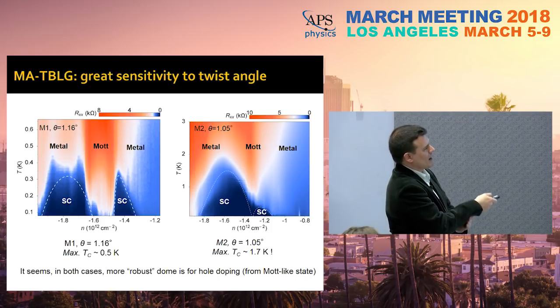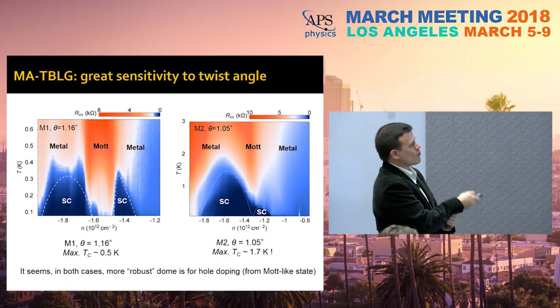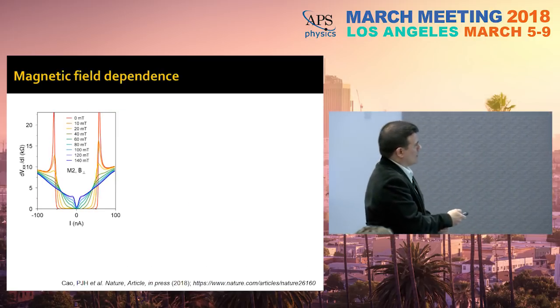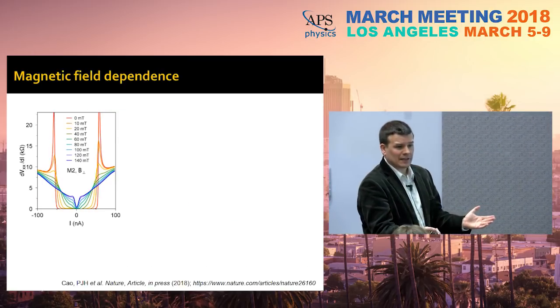There's a bigger asymmetry now. This has actually a much higher TC at optimal doping of about 1.7 Kelvin, okay? We seem to always have a more robust dome for holes than for electrons, very similar to the cuprates. But we can, of course, apply magnetic fields to these systems, okay? We can kill the superconductivity.